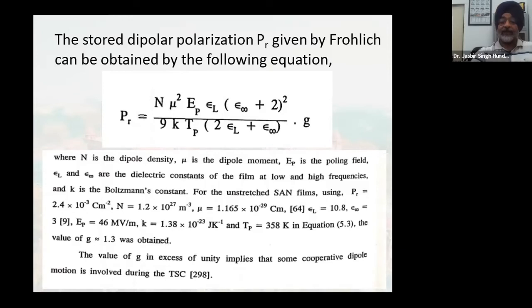So we have poling fields. G was found to be around 1.3. Look here. So this showed that the value of G in excess of unity implies that some cooperative dipole motion is there in the field. Now this was established through TSC studies. We knew N, we knew dipole moment, we knew the poling field, we knew the dielectric constant at low and infinite, very high frequencies. And putting in all those, we knew K, we knew TP, we knew the value of PR as we obtained from TSC studies.